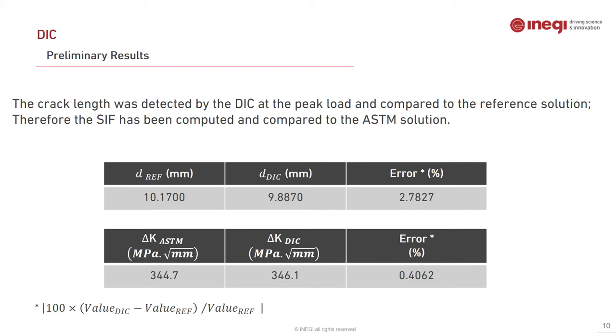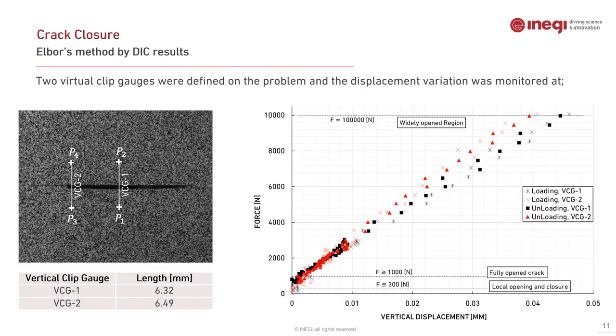I must mention that the stress intensity factor for the digital image correlation has been determined through the overdeterministic algorithm, basically using the Williams series expansion and also the singular value decomposition equation.